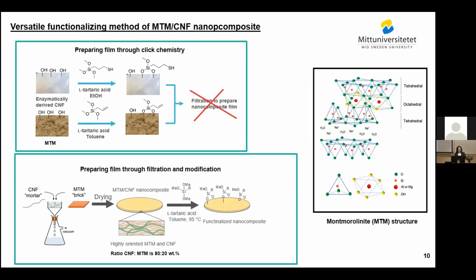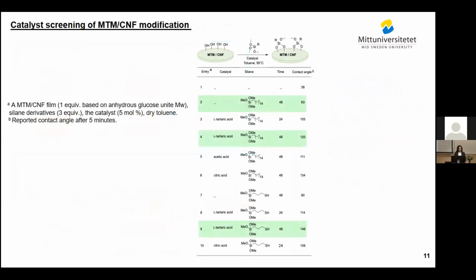But then in the following, we did the modification of this nanocomposite with the alkoxysilane in the presence of tartaric acid, in toluene at 95 degrees. Here is the catalyst screening of the modification. Here we see that comparing entry 2 and entry 4, we have a high value of the contact angle when we had just the catalytic amount of L-tartaric acid.